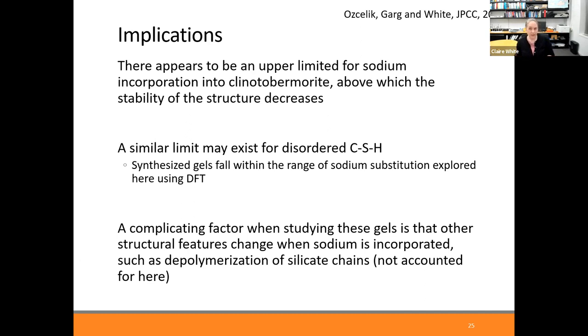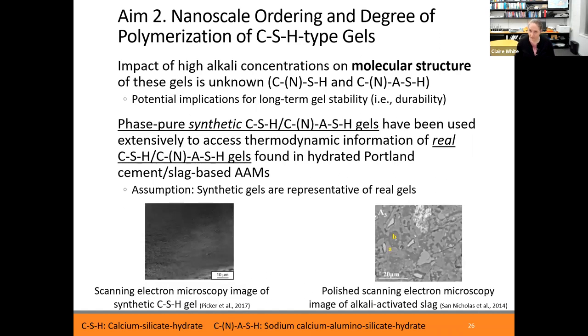So what I should mention, though, there are a bit of caveats from the study that we've done, because there are other differences that we know that occur when sodium's added to the system in terms of the structure of the gel. So what I showed previously a while ago was I told you that the silicate chains in CSH gel, the conventional gel, are finite in length. When you add sodium into the system, it is known that these chain lengths get shorter. And so this will also impact the thermodynamics of the gel, which we haven't actually looked at with these computational calculations. But on the next slide, we're going to look at this from an experimental viewpoint.